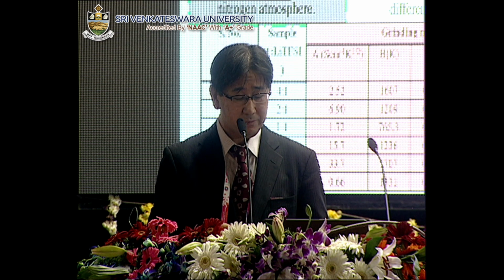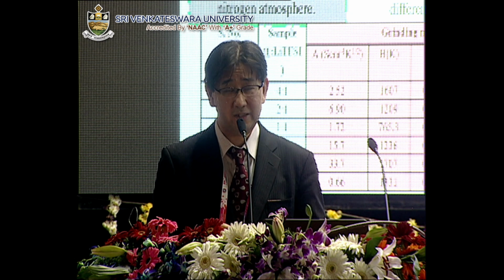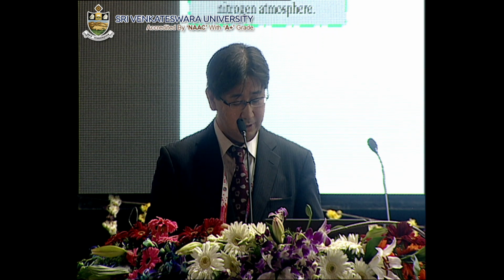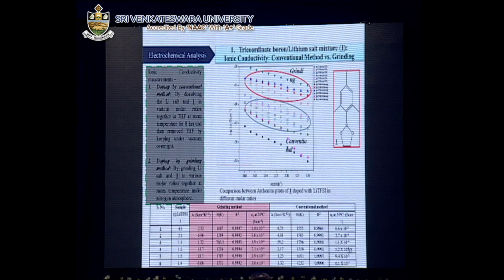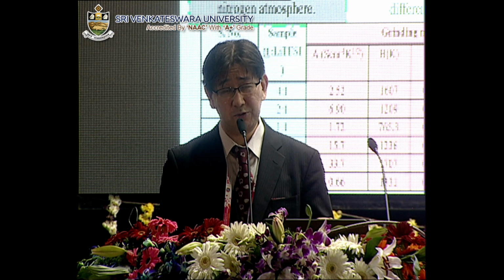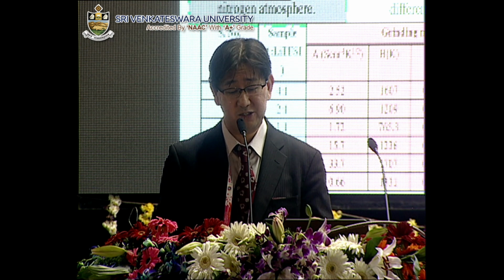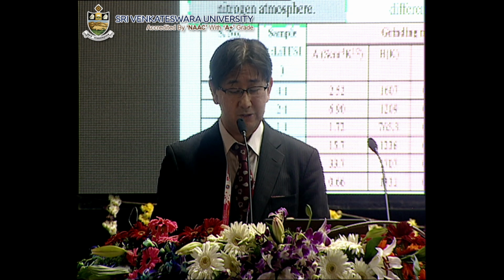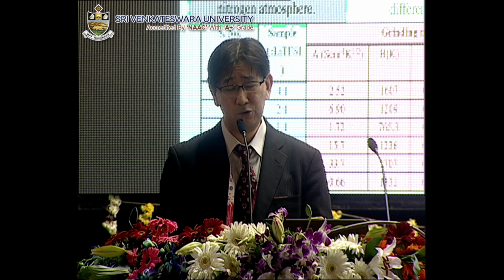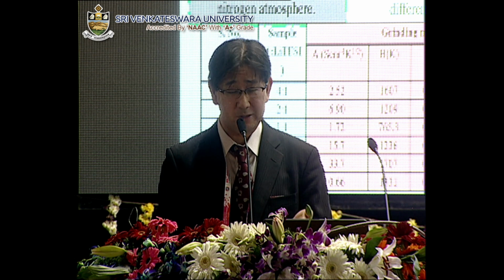The second method was doping by solid-state grinding without using any solvent, carried out under an inert atmosphere. Interestingly, the samples prepared by solid-state grinding showed fairly high conductivity values compared with the samples prepared by the conventional method. Such enhancement was observed only under a specific composition of boron compound and lithium salt. Under such compositions, the activation energy of the ionic transportation was found to be very low, indicating that the presence of the solid-state crystalline boron compound is fairly important in achieving